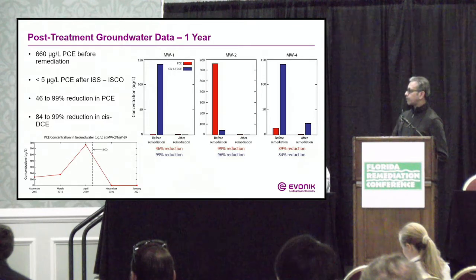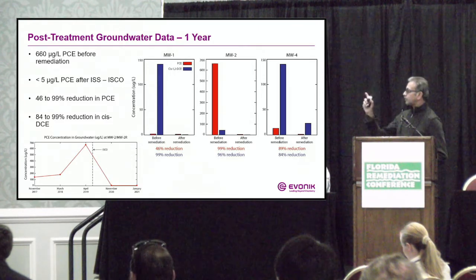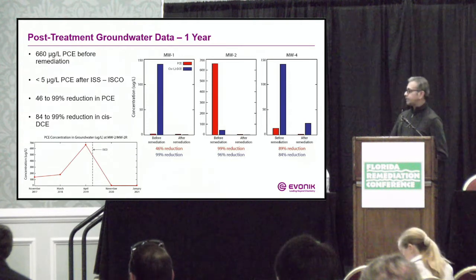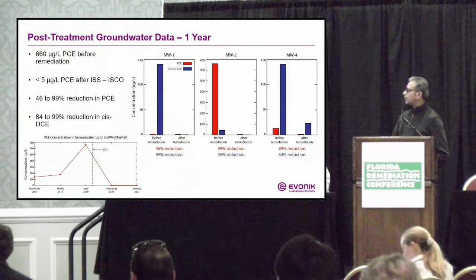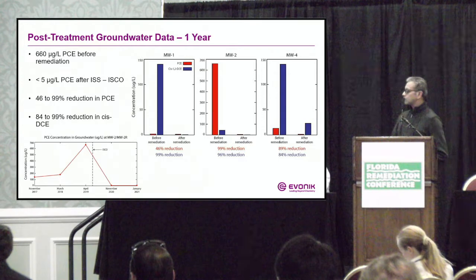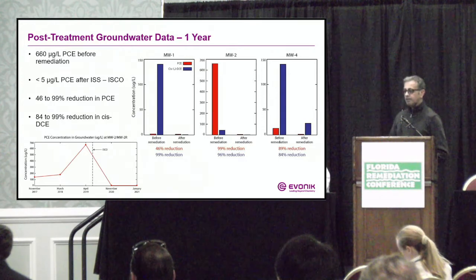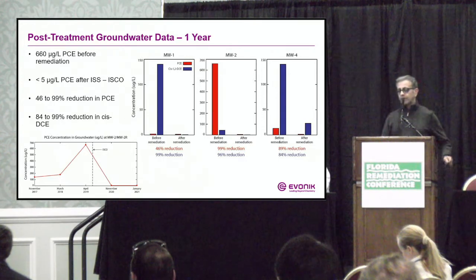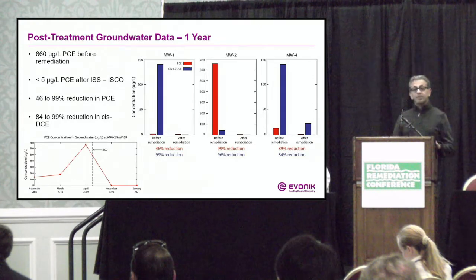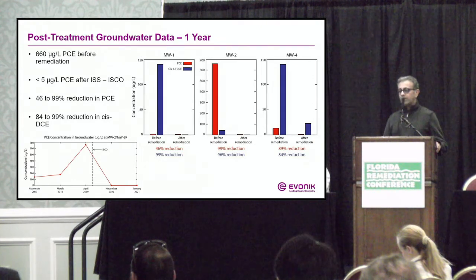Monitoring well 1 was primarily cis-DCE. Monitoring well number 2 was primarily PCE, which is the red bar. And monitoring well number 4 was a mixture of PCE and cis-DCE. In all, we got about 46 to 99% reduction in PCE in these wells, and about 84 to 99% reduction in cis-DCE in these monitoring wells.